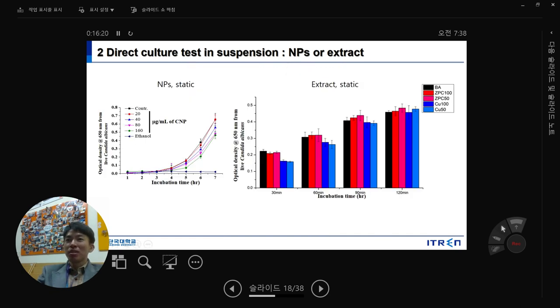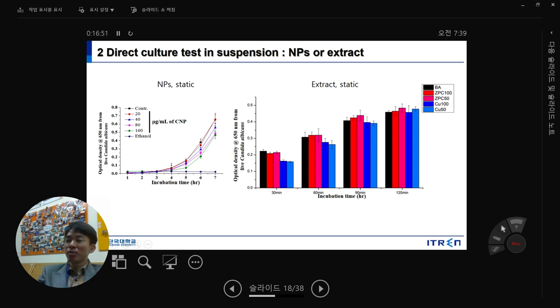As an example, we cultured Candida albicans (a fungus) with nanoparticles at various concentrations in static 96-well plates and measured optical density over time. Compared to the control (black), the red and green groups showed slight inhibition of growth. We also tested direct nanoparticle treatment on fungi and used extract from cement incorporating copper to check antibacterial effect — the copper-incorporated extract showed inhibition over time. You can use either extract conditions or nanoparticles directly to investigate antibacterial effect.